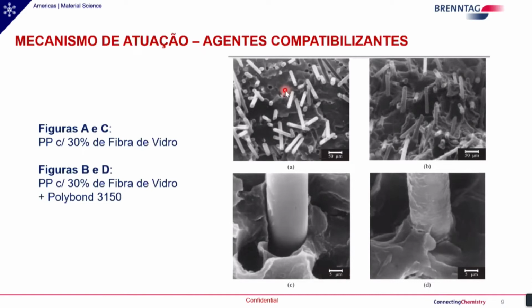It is the use of glass fibers in a polypropylene composite. This is a polypropylene resin. Here in images A and C, we have the material without the agent. We can see that the fibers are removed. We see the holes right here, the voids, the empty spaces. This shows that when we analyze the tensile strength, these fibers have been removed. This image C is very interesting. This is the fiber without the compatibilizing agent, and it looks loose in the polymer.